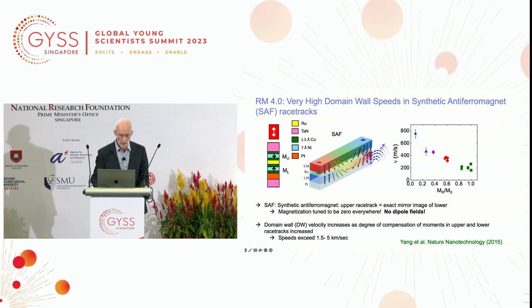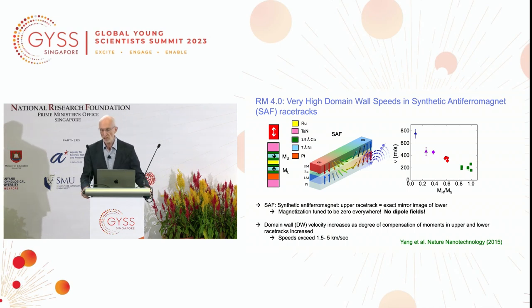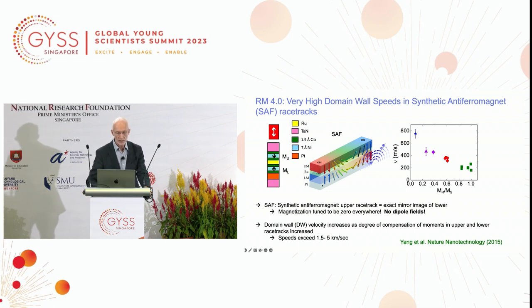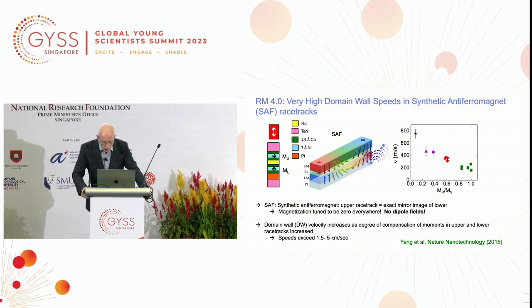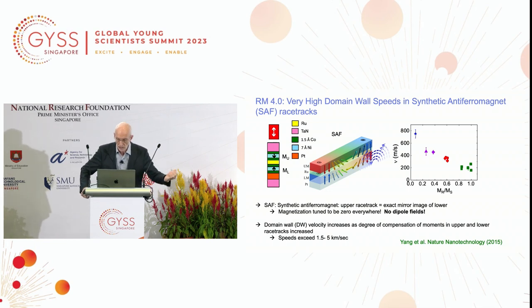So if you look at this cartoon, you see here is a lower racetrack where the magnetization rotates from up to down. You end this with a chiral, this is actually a Néel wall because the moment here is pointing perpendicular to the transition. We create on top a second racetrack, which is exactly a mirror image of the lower one. So the moment in the lower racetrack is exactly mirror imaged by an opposite moment in the upper racetrack. In this way, all along the racetrack, the net magnetization is zero, and we can eliminate the dipole fields. Without this, we cannot build any type of magnetic device. And this actually was an invention of mine based on my discovery of long-range oscillatory interlayer coupling.